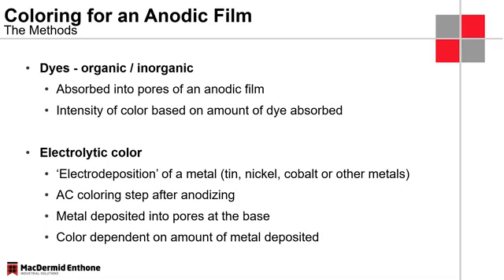Another way of achieving a colored surface is by using an electrolytic color, and these are mainly based on metals such as tin. So I think that's probably the biggest sector here, and there are others that utilize nickel and cobalt and some other metals to get different shades of color. This is done in a tank with AC power, so it's an alternating current source. And what it does is it deposits a small amount of tin onto the bottom of these anodized pores, and then when the polarization changes, it actually oxidizes the tin layer.